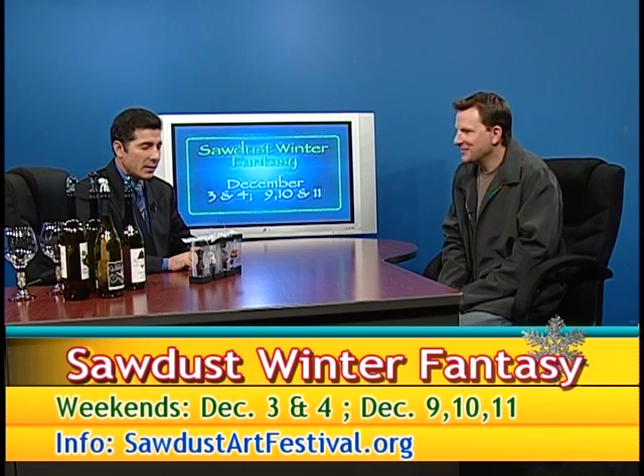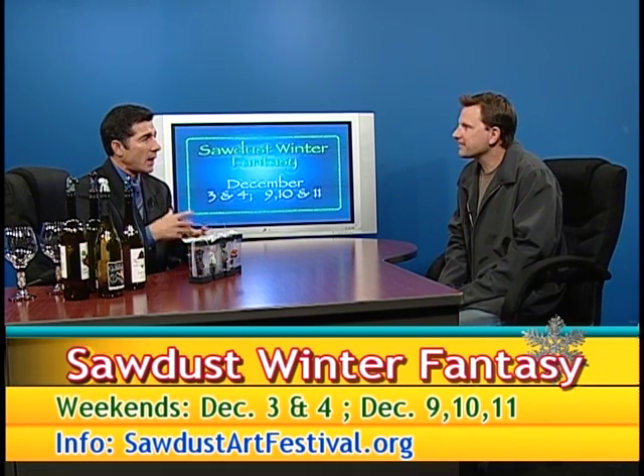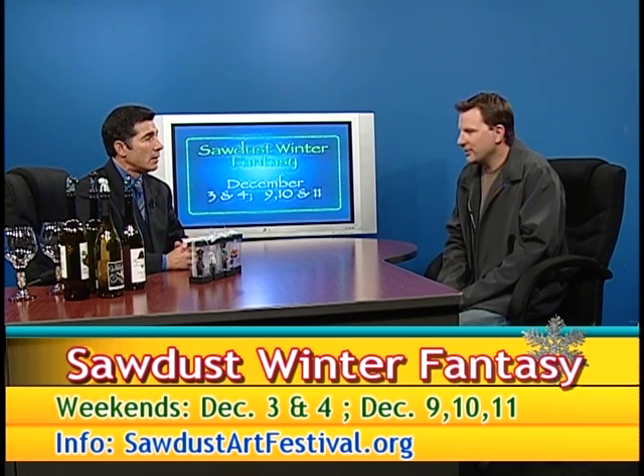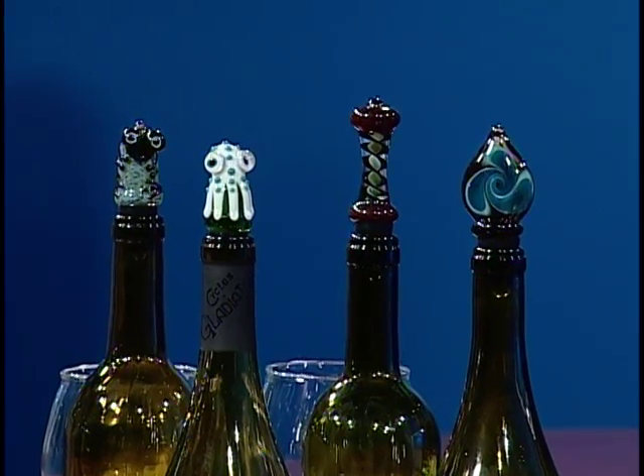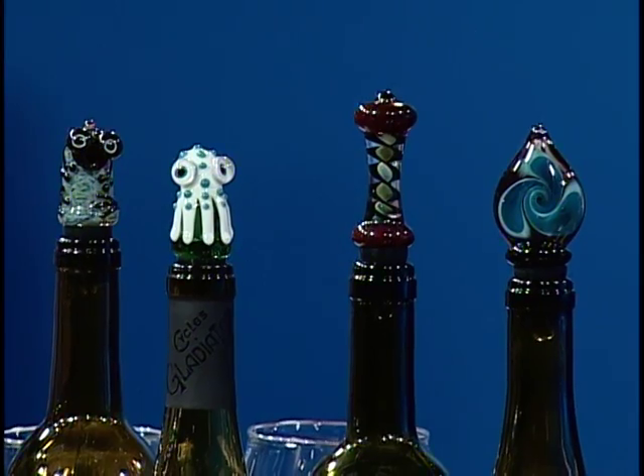Wow, that's quite amazing. Do you have to fire these once you've already molded them and developed them, or do you just wait for them to harden? No, I absolutely do. I make them on my torch, and then when I'm done, I put them in my kiln at 1,050 degrees. They'll sit there throughout the day, and at the end of the day, I let it run an additional couple hours, and then I'll shut it off. And come morning time, I get to pull out all my glass.